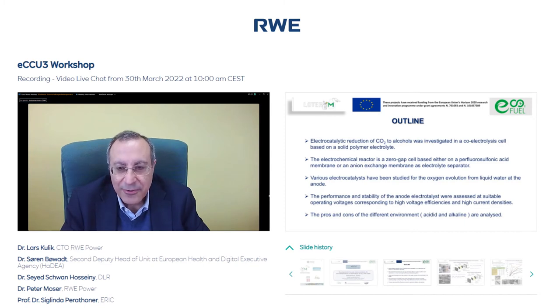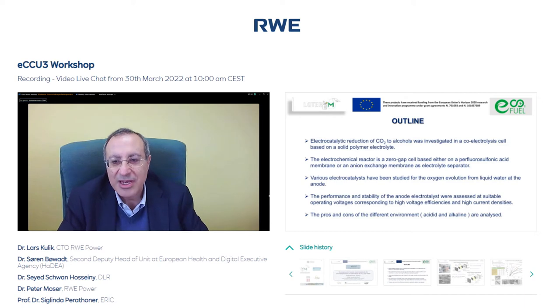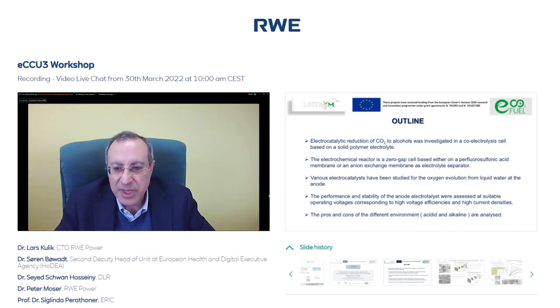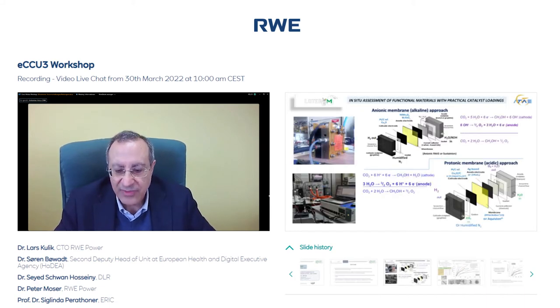Next slide, please, slide number two. So the outline of this presentation is essentially regarding the oxygen evolution process, but in a context where we have also carbon dioxide reduction. And our analysis is essentially regarding the screening of the electrocatalysts in a zero gap cell based on perfluorosulfonic acid membrane or an anion exchange membrane as electrolyte separator. So the aim is to understand the electrochemical performance, the electrochemical behavior for the oxygen evolution in these two different environments in order to get information on the energy efficiency and also clearly understand which is the advantage of the alkaline versus the acidic environment and vice versa.